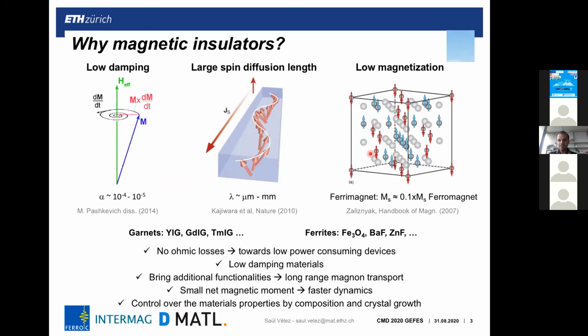But also, plenty of these materials exhibit ferrimagnetic or antiferromagnetic order, meaning that the different sublattices in the material couple antiferromagnetically, and the net magnetic moment is lower than in ferromagnets. This is useful for spintronic devices, because the dynamics you can induce in these systems are much faster. For instance, in domain wall motion, you can drive domain walls much faster because the magnetic moment is reduced. Apart from that, you can also tune the properties of the materials by chemical composition and growth. That's why we would like to work with magnetic insulators.